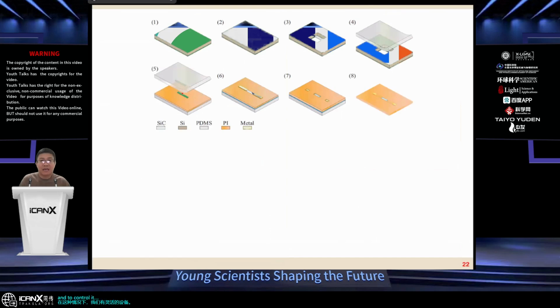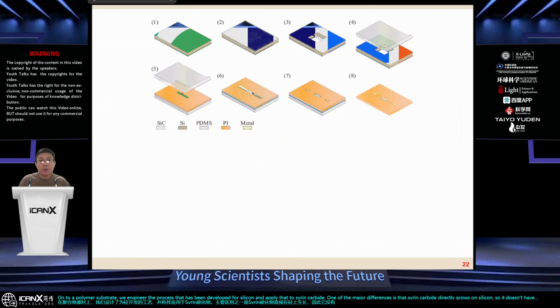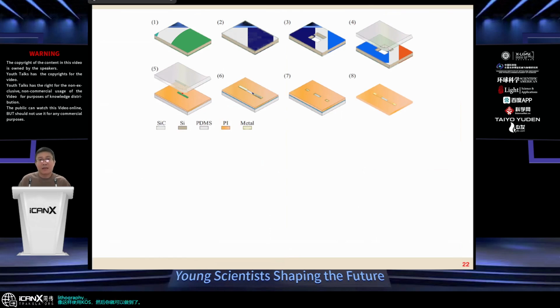And to controllably transfer silicon carbide from silicon onto a polymer substrate, we engineered the process that has been developed for silicon and applied that to silicon carbide. But one of the major differences is silicon carbide grows directly on silicon, so it doesn't have any sacrificial layer. So the way we transferred it was to make a silicon carbide freestanding membrane on silicon using KOH like this. And then you can do lithography directly on silicon carbide and dry etching to make silicon carbide microstructures, freestanding. And you can use a PDMS stamp to pick this structure from the silicon substrate onto PDMS and then further transfer it to polyimide.